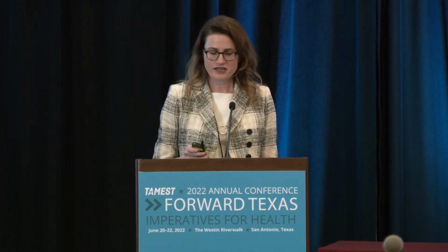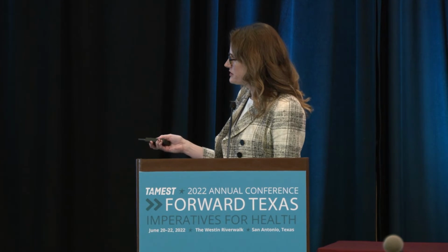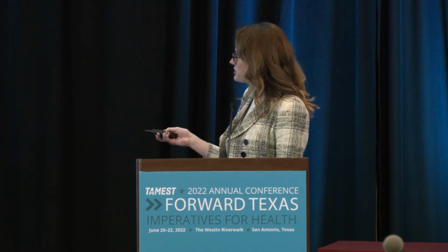So this is some example data that we got for this polymer PTMA. It's in a lithium triflate electrolyte, so we still have lithium there, but we don't have cobalt or nickel, so we're doing a bit better. And to study the way it works, we apply a triangular voltage wave here. So we charge it and discharge it. Meanwhile, we get peaks and valleys in current. That's commensurate with storing and releasing charge.